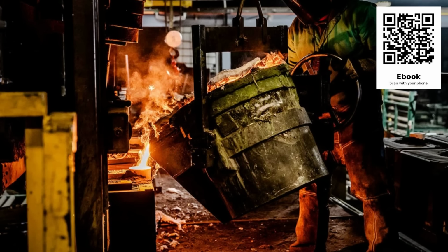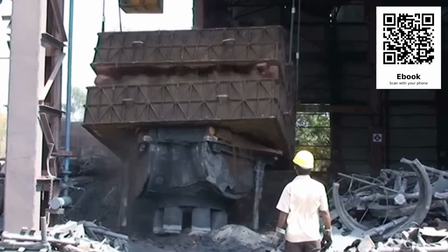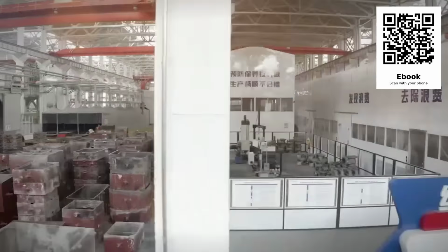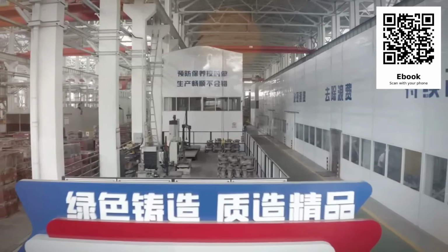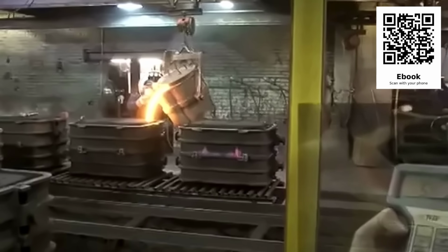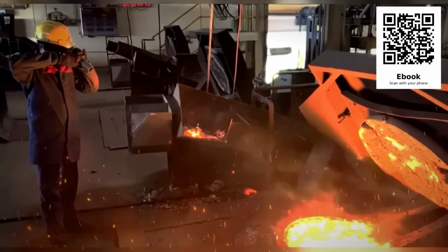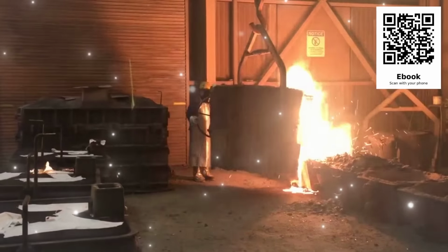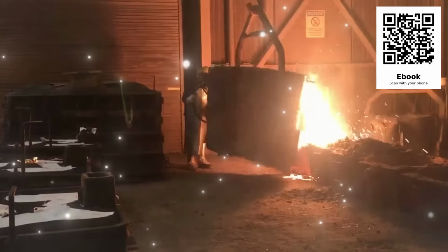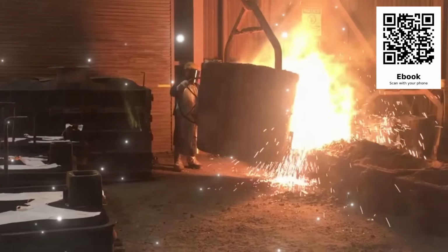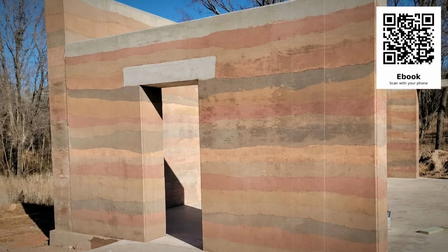The foundry industry, by the way, is the one place in modern American manufacturing where silicate-bonded sand is in continuous, large-scale use. Every metal casting that is poured in a sand mold in this country is poured into sand that has been bonded with sodium silicate or a closely related chemical. The molds hold the shape of the casting until the metal solidifies, and then they are broken apart to release the part. The strength of those molds, the precision they hold, the resistance to thermal shock when molten iron at 2800 degrees Fahrenheit is poured into them, is a testament to what silicate-bonded sand can do. And yet the same chemistry, applied to a wall or a floor or a foundation, is treated as folk wisdom rather than engineering practice.